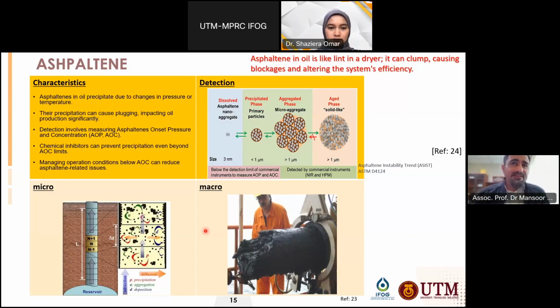For the detection part, as you can see, this classification is for when the size of micro asphaltene is 3 nanometer to 1 micrometer. We cannot detect it, or the measurement cannot be done, by AOP or AOC, but the detection can be done by commercial NIR, which is near infrared, and high pressure microscopy to identify the asphaltene flocculation. We can also use particle size analysis techniques, and there are other references. For example, the asphaltene instability trend from this reference can be used in order to detect asphaltene.